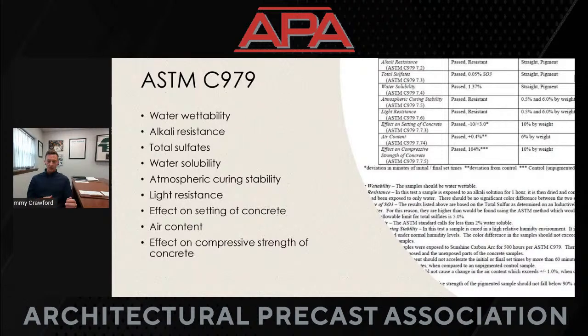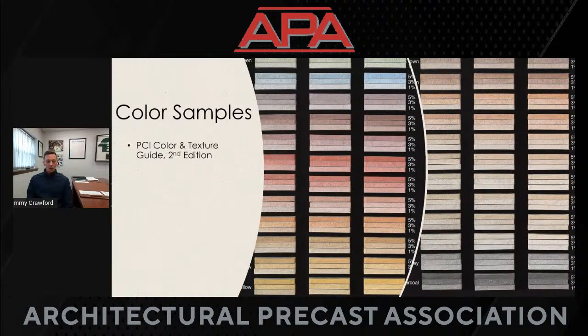Effect on the setting of concrete. You cannot cause a material delay in the set time of concrete. It cannot change the air content of the product too much or too little. Effect on compressive strength. If you put your concrete in the chamber and press down on it till it cracks, you cannot cause an effect on compressive strength. All the pigments that DCS sells and are commonly used in the industry should pass ASTM C979 when used at the prescribed dosing rates. Color samples, I included the PCI color and texture guide here.